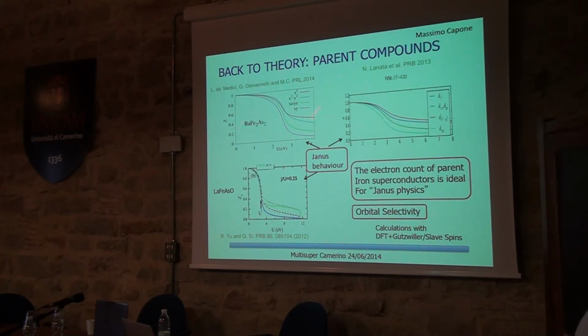So our theory essentially here, I'll just show you, these are the parent compounds, and we get the same thing that I described before. That was before for the model system, now it is for the iron-based superconductors, and you see the two-step thing. First you go down very fast, and then you get something flat. So we are in that regime. This is done in a realistic way.